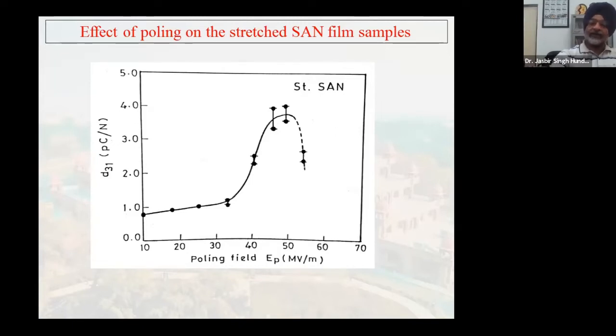Please remember here, the film had been annealed at 80 degrees centigrade for 15 minutes, and it was stretched to a ratio of 2.5, right? So other factors have to be kept constant if you are varying one particular thing. If you are looking at the variation of D31 with the poling field, the other parameters will have to be kept at optimum values. Okay, so that's how things are done.